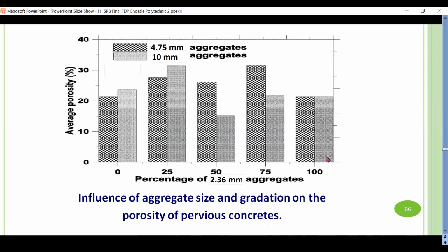So this is the influence of aggregate size and gradation on the porosity of pervious concrete. If you go on increasing the percentage of a smaller size particle, as I told you, it depends on the requirement. The finer aggregate can be added in a very small quantity. A study has been carried out where the percentage of 2.36 mm size was varied from 0 to 100% for two different size aggregates, one 4.75 mm and another 10 mm. You can see here that for 25 to 75%, the average porosity is large compared to 0 and 100. So while proportioning it, we have to consider these factors also.